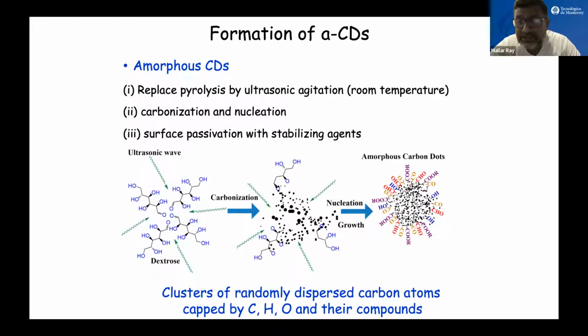We replaced pyrolysis by simple, very long-term ultrasonic agitation of carbon precursors. We can do it with glucose, dextrose, we can even do it with coal. Of course, it requires purification, which again leads to carbonization, nucleation, and then surface passivation. In fact, we are able to passivate it by the reagents which are already present, like hydrogen, carbon, oxygen. We can also passivate from outside by, say, amines, or by nitrogen-containing groups, or sulfur-containing groups, or many other groups.